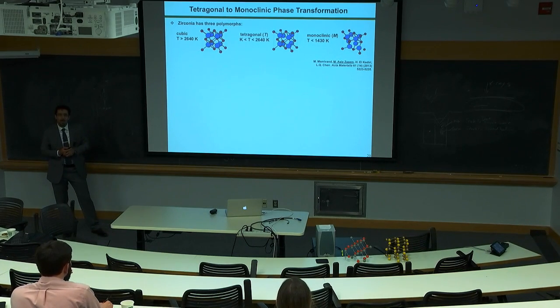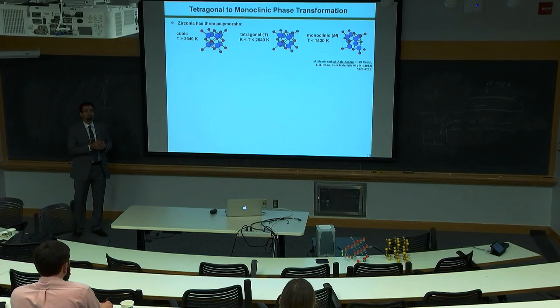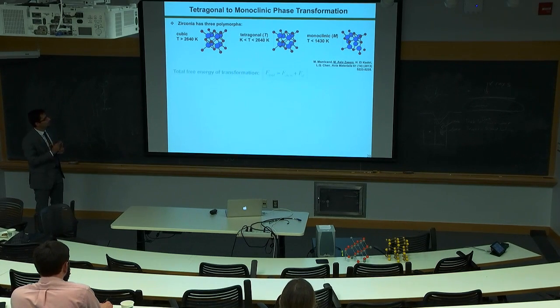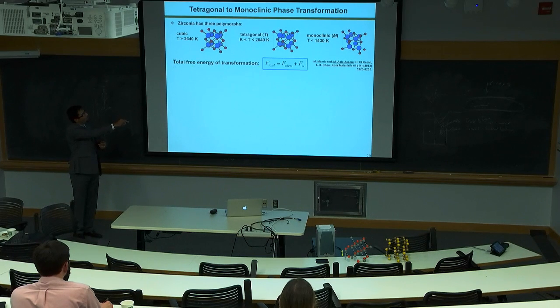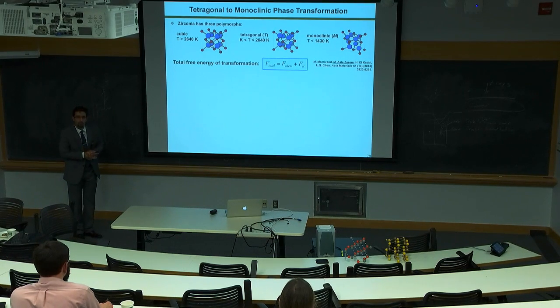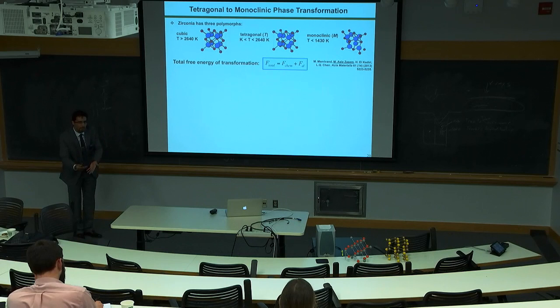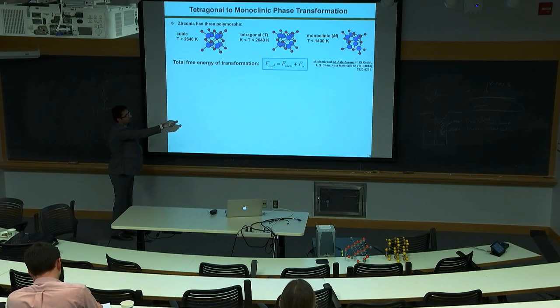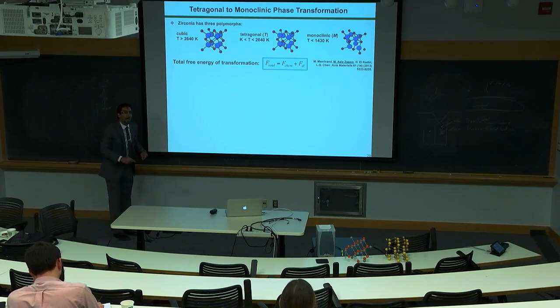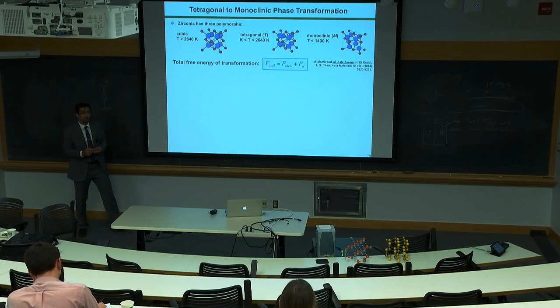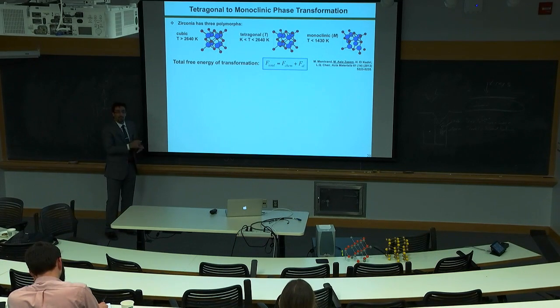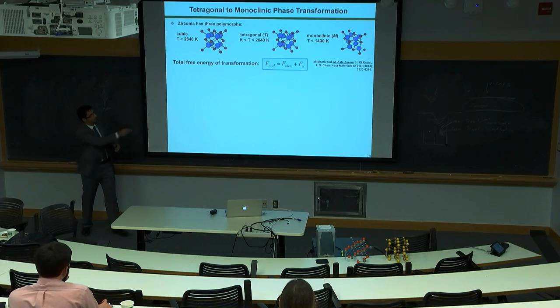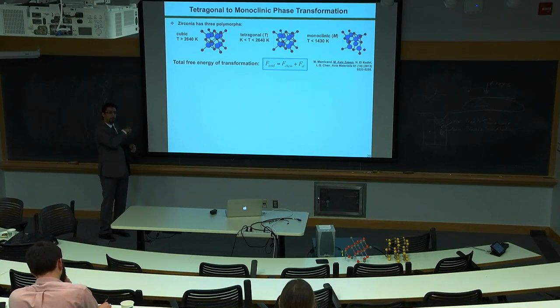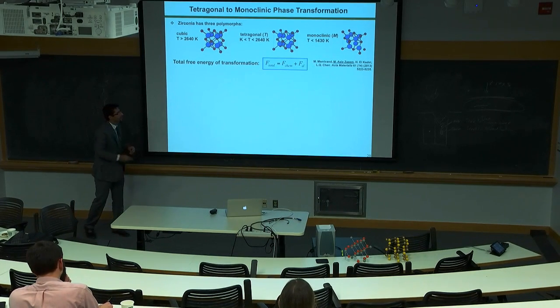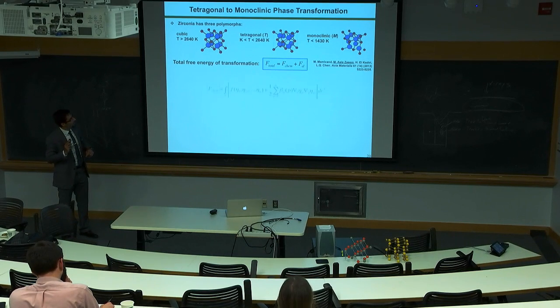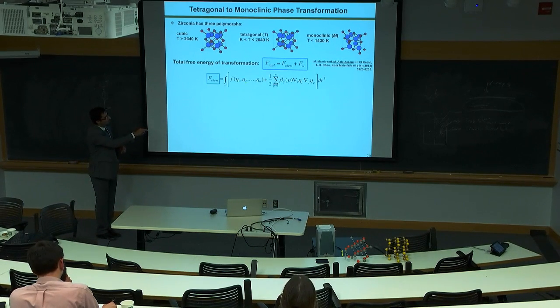So based on that, how many phase field variables do we need? 12. Okay? So again, we need to build a total free energy functional. Starting from the same step, instead of having one term, we now have two terms because we are in the solid state. At least we are going to have elastic strain energy developed. This was very similar to the previous one for solidification. Now we have this added. This is the chemical free energy, eta 1 to eta n.